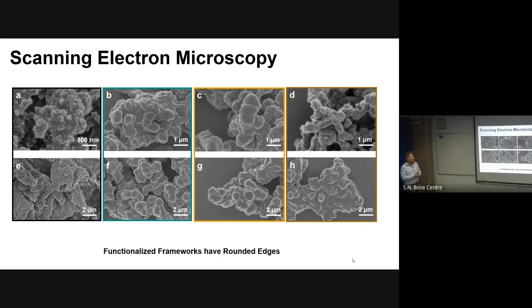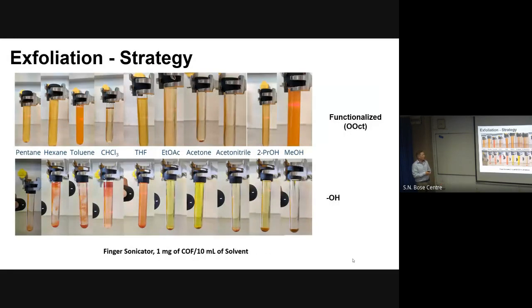Okay, so we still want to exfoliate our materials. What we can see here is from scanning electron microscopy images. Here's the non-functionalized material. Here are the three materials with the side chains. And what you can essentially see is that the functionalized materials have more round edges. They are not as crystalline, and the non-functionalized material has very sharp edges, a bit more crystalline.